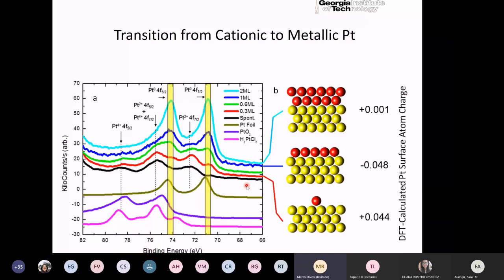All right, but then there's not a mixture of copper with the other metal? No, the copper is replaced by the platinum. In this case, we do not see any copper remaining. So copper is an intermediary that is used as a way of decorating the locations where the platinum will go, and since platinum is more noble than copper, it essentially spontaneously replaces it. You can follow that reaction by watching the potential of that electrode, and that potential of the electrode changes and equilibrates to the electrode potential for platinum surfaces. It starts out as a copper surface and then it ends up being a platinum surface. And when that becomes asymptotic, that's when you stop. And then when you do something like XPS, you don't see copper on the surface anymore. Yeah, it makes sense. Also because it's too little. Okay, thank you so much.